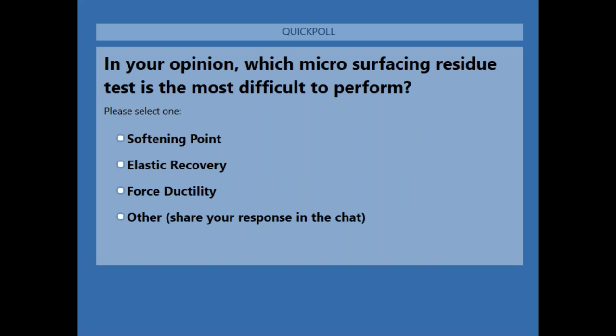But if those of you who have done high temperature recovery, whether it's a distillation, most of the microsurfacing distillation, you'll notice that the residue is kind of a black cottage cheese. So it's not easy to pour. So we'll see what the results are. What have they come up with, Antonia? So if you don't agree with any of these three, you think there's a different test, remember to share your response in the chat. But we have 15% of the attendees saying that it's softening point that is the most difficult. 24% are saying elastic recovery, and then 61%, the majority, are saying that it's force ductility that's the most difficult to perform. Okay. And then share your thoughts in the chat if you disagree.